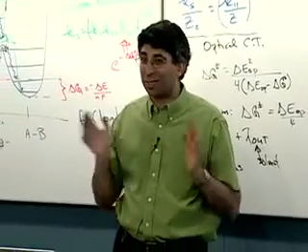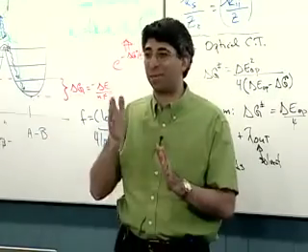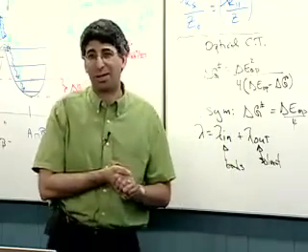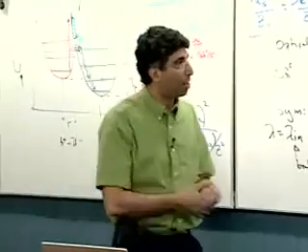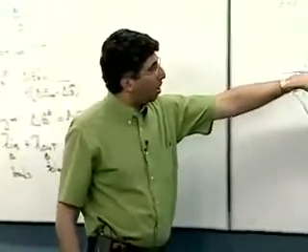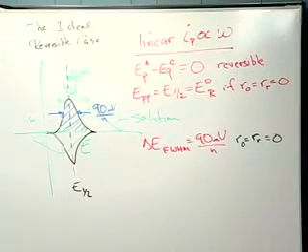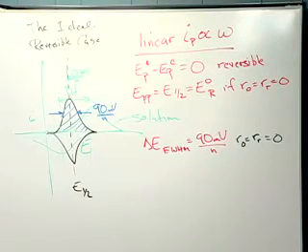And that doesn't mean it's not on the surface and it's not reversible, because once more you have that IR loss that can come into play in these systems. I also can run into an issue if my activity coefficients are non-zero and not equal to each other. That is, my nearest neighbor interactions.